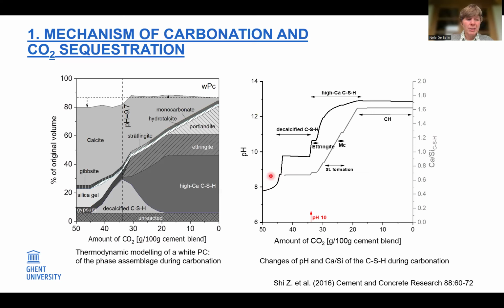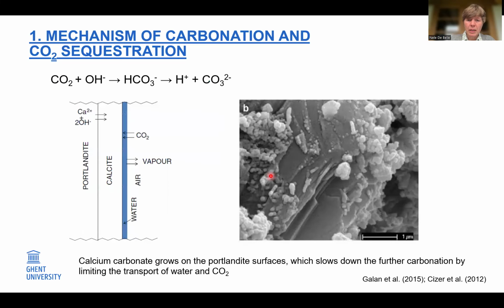Well, actually, the same carbonation sequence is observed in Portland cements blended with different types of SCMs. However, with the reduced content of Portlandite, carbonation more rapidly affects the CSH and the CASH phases, and this contributes to a coarsening of the pore structure, whereas in normal Portland cement paste, rather a pore consolidation of smaller pore structure is created. We can also see that in reality, the Portlandite carbonation may be incomplete due to covering by calcium carbonate crystals, slowing down the further carbonation reactions.